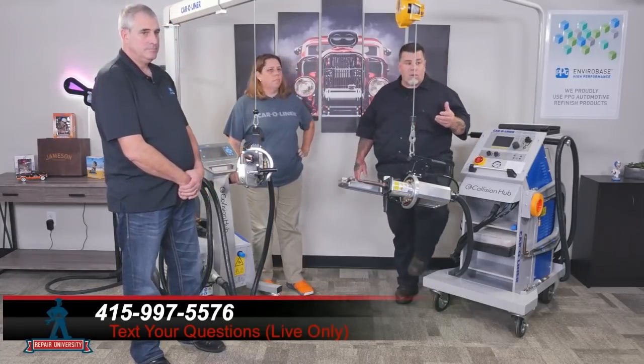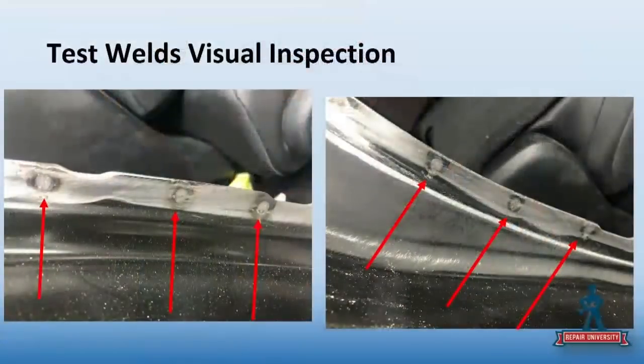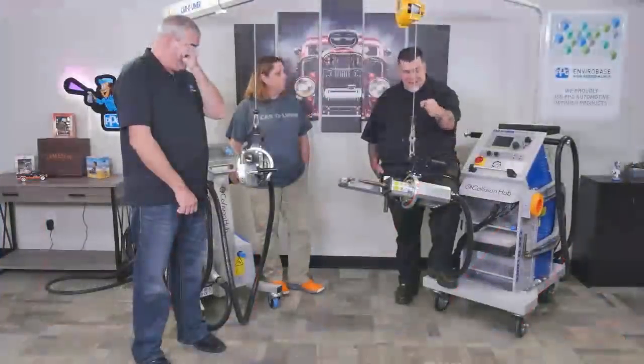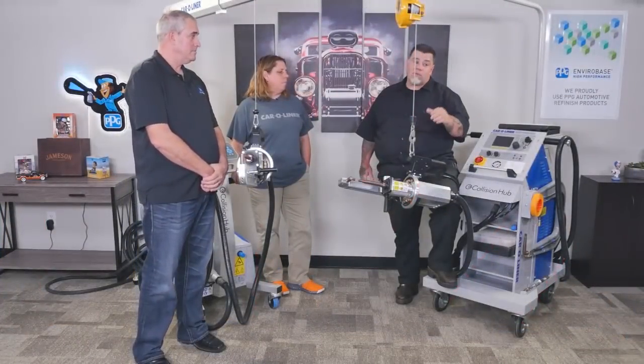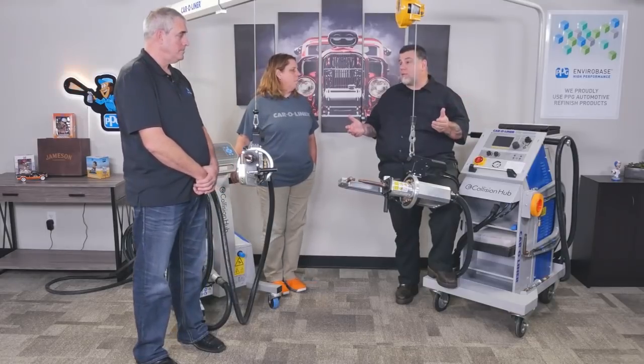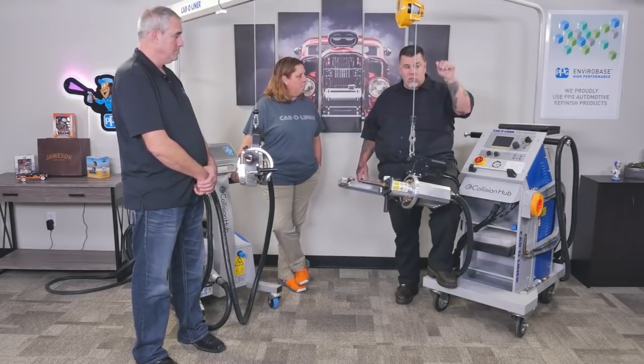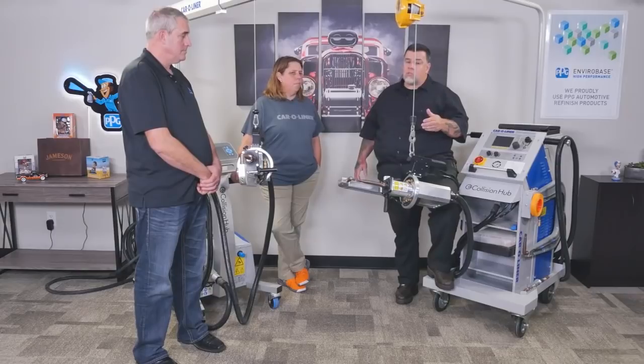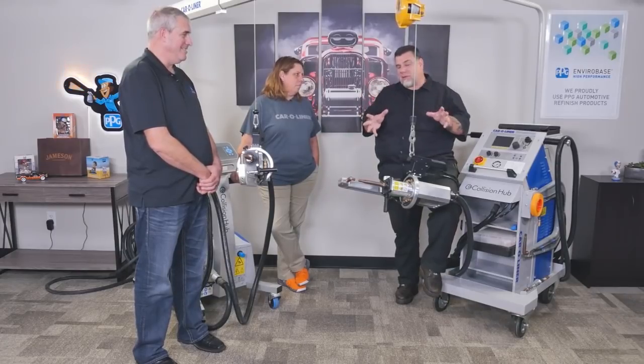Now here are welds with just heat marks. It had enough applied heat, but you can see there's really not a deep indentation, and there's a little bit of an area that looks like a circle, and areas that don't have anything but a shadowing mark. These welds were easily broken with a screwdriver and just my hand twisting it. I wasn't even taking a wedge test like Honda used to have, a piece of wood with a wedge you shove in between to see if they pop, which they shouldn't. Not agreeing that should be done on the car.